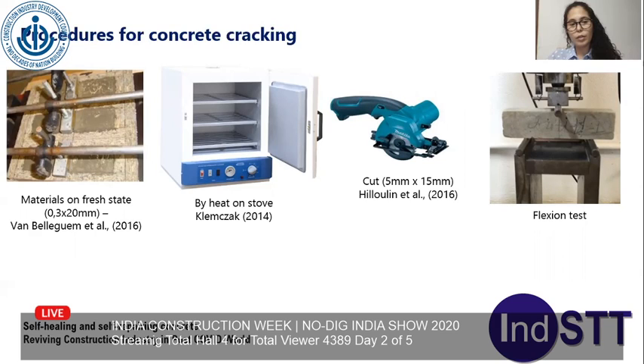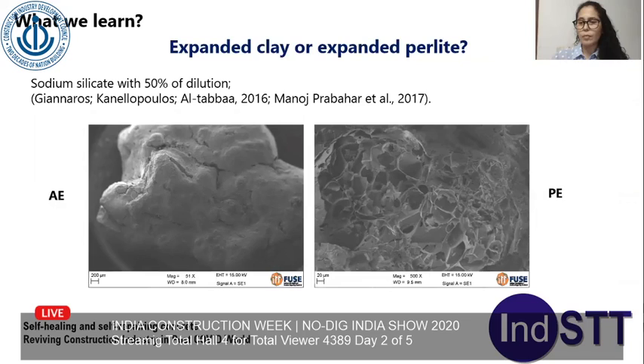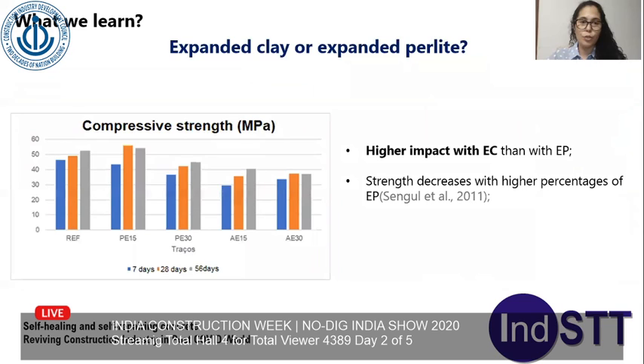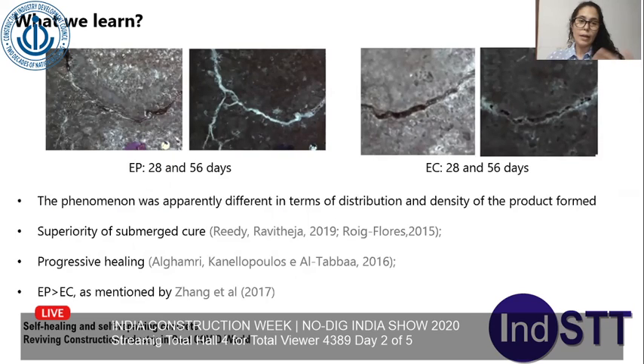What we learned in my research group here in Brazil, first of all, we were comparing expanded clay and expanded perlite from Brazil, and we checked by the same analysis that expanded perlite has many more voids, so it may be good to put the chemical and bio solution. There's also a higher impact when we use expanded clay than expanded perlite, so expanded perlite may be better to not damage the concrete properties. And by microscopy analysis, we checked that expanded perlite is better to conduct the continuous healing inside the crack.